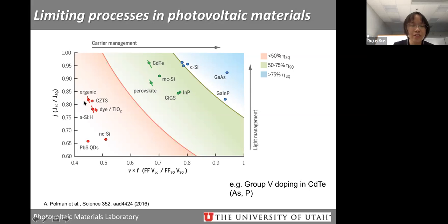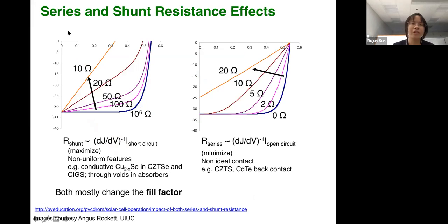For some silicon, some materials we have, we can reach 18% of current potential, but the voltage and fill factor potential is less than some good solar cells. We have 19%, but most of the solar cells are 17%, even 14.5%. Group 5 doping in cadmium telluride increased the minority carrier lifetime a lot. So the recent efficiency improvement can be reflected by this. So it shows how we optimize the solar cell.